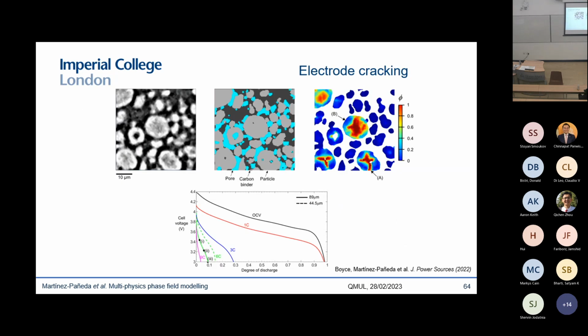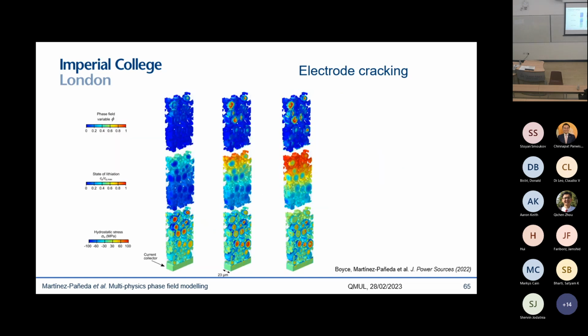And you can see here, this is a 2D segmentation image, so you can see the image that you get from the XCT, how the segmentation process goes, and then how in your finite element problem, you're predicting for a realistic microstructure, what is the propagation of that. Here are some representative 3D results. Again, here, for example, we were changing the thickness of the electrode, and we can see that it's a very heterogeneous response, both from the electrochemical and the fracture behavior point of view.